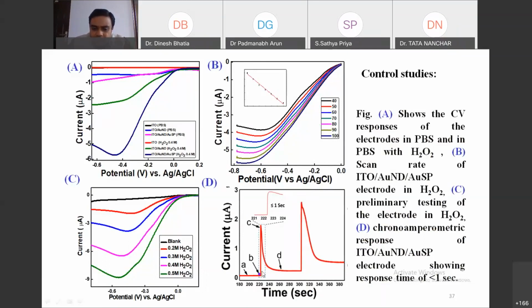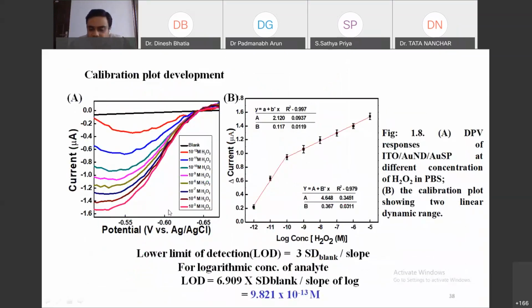If I say, you can see in 1 second, or more precisely in less than a second, it is giving a signal response. That is only because of the incorporation of such three-dimensional nanostructures in the matrix. So this is the beauty of these materials in the sensing matrix. Even in less than a second you can get a signal output. After this, we have done the calibration response.